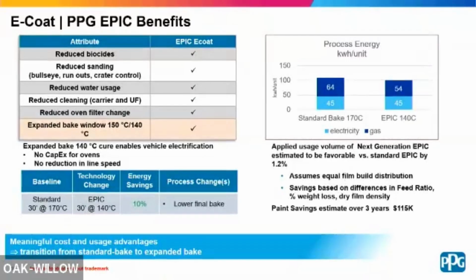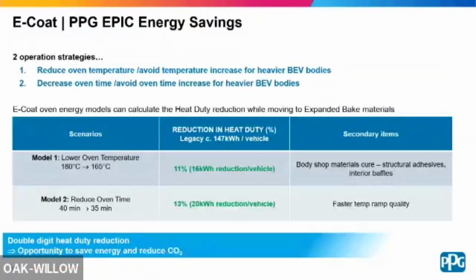Now, there's not a one-solve solution for everything, and everybody knows it. If you work in production, you know it. So in terms of electric ovens, you're pretty much not going to notice a difference. You'll notice the difference in a gas oven. But what people really care about is the math. So we take a gas oven and we lower the temperature 15 degrees. You'll achieve a reduction of 11%. However, if you reduce your oven time by 5 minutes instead and keep your oven temperature the same, you can get a 13% efficiency.